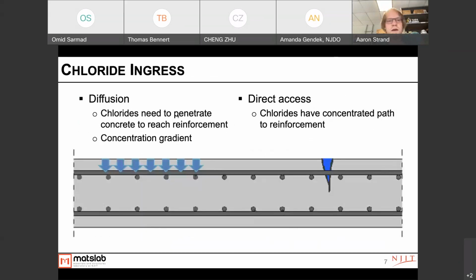There are two different mechanisms by which chlorides can get in. Typically, we see chlorides through the diffusion mechanism, where chlorides need to penetrate the concrete to reach the reinforcement, and this typically creates a concentration gradient. There's also more direct access, where the chlorides have a concentrated path to reach the reinforcement, and this is typically found through cracking of the structure.